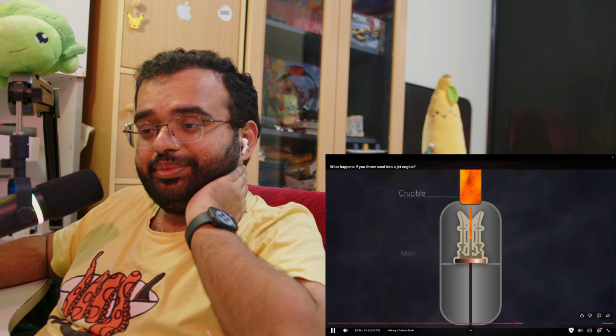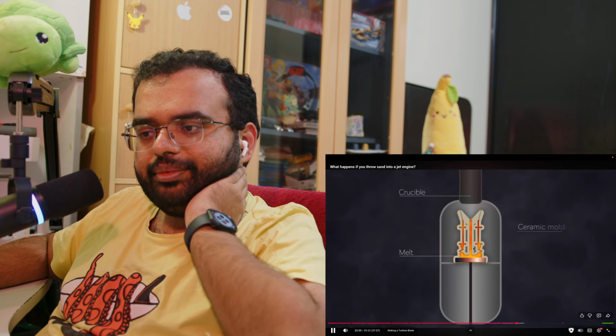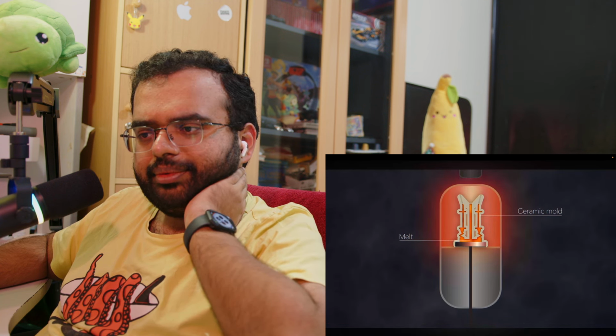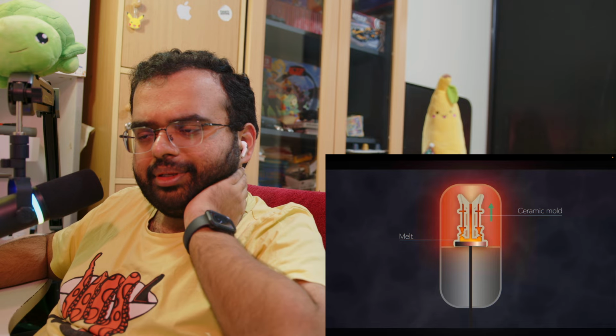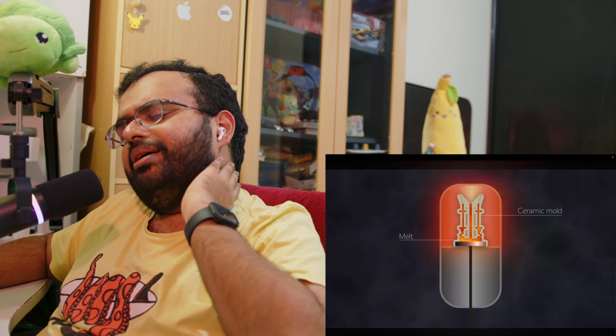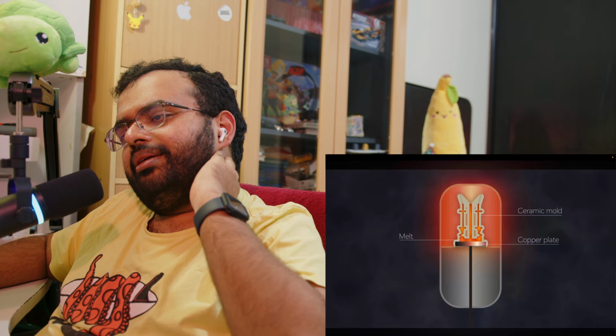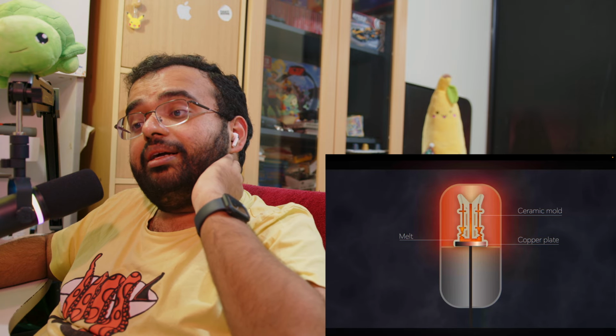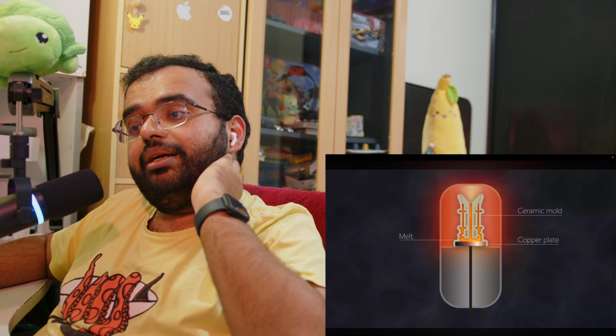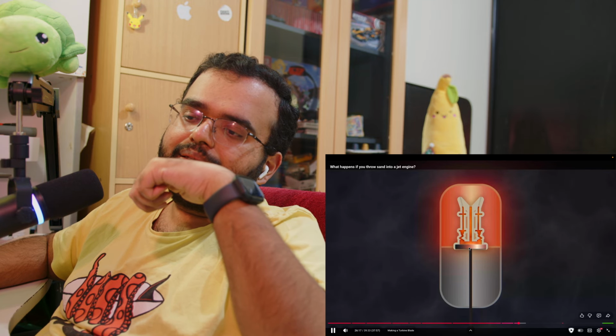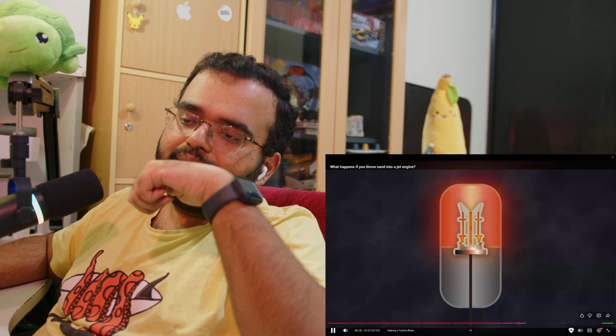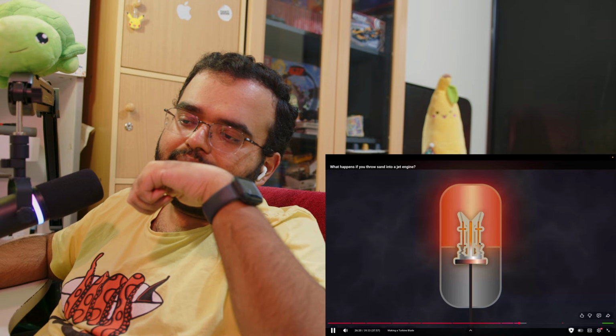You start by pouring molten superalloy into a ceramic mold that's mounted vertically and heated to about the same temperature as the melt. The mold fills from the root up toward the tip. At the very bottom of the mold sits a copper plate cooled by water. Its surface is patterned with tiny grooves that act as nucleation points for the first crystals to start to form. It's here that solidification begins. Then the entire mold is slowly lowered out of the hot zone, so the solidification continues in just one direction.